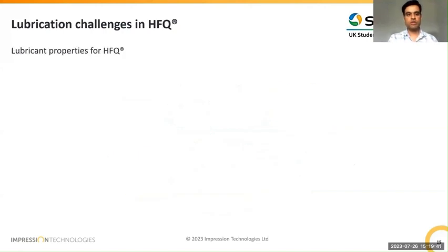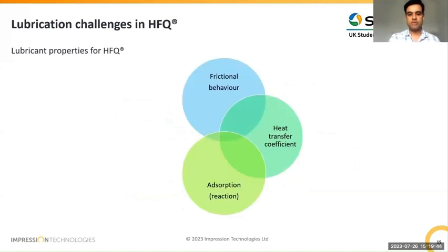So that brings me to what should be the properties of the lubricant. The three most important properties, which are probably common with lubricants in other fields in tribology, are, first, frictional behavior. We want the friction to be predictable, constant and consistent. Then, because we are trying to lose heat, the lubricant should help us lose heat as rapidly as possible, so it needs to have a high friction heat transfer coefficient. And finally, the lubricant should be able to stick or adhere very rapidly to not only the tool steel that it is being sprayed onto, but also the aluminium. And that can happen either through absorption or with some reaction elements.